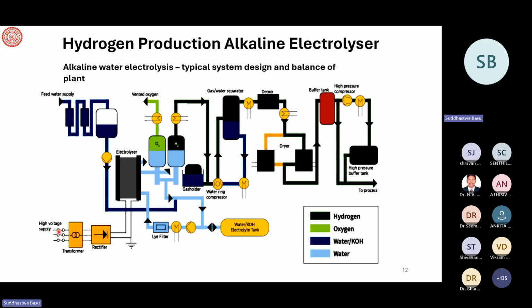Here at the bottom is also very important: giving the minimum but required voltage. You get the high voltage from the power supply, like a high voltage power line. If it's not photovoltaic, then you have to have a transformer and rectifier, because this is an AC supply and what you require is DC. So AC is converted to DC by the transformer rectifier, and you have to have a very good, constant voltage range, no fluctuation, so that all the time electrolysis takes place at the same rate, and water and unreacted